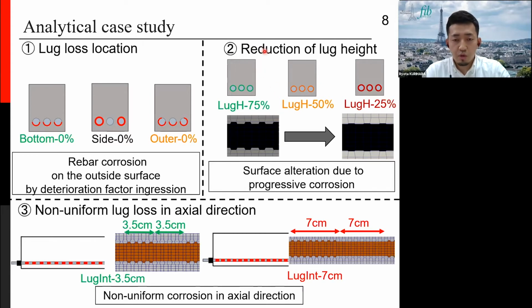Case 2 aims at the condition in progress of corrosion, that is, the section loss of the rebar occurs by corrosion, but the roughness by the reduced lug shape remained. Three levels were set: 75%, 50%, and 25% of lug height. And case 3 focused on the non-uniform corrosion in the axial direction. Cases where complete lug loss and sound areas existed alternately were analyzed, and 3.5 centimeter and 7 centimeter intermediate lengths were set.